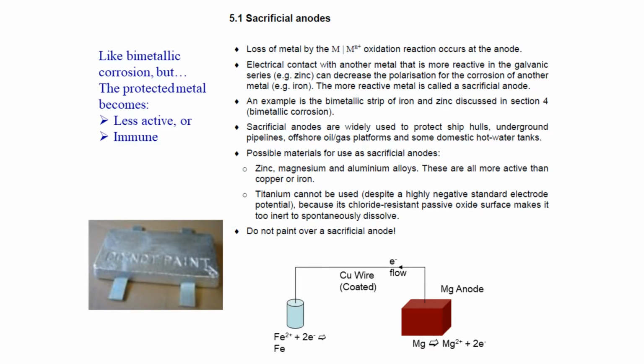Section 5.1 on sacrificial anodes talks about basically bimetallic corrosion. In chapters 3 and 4, we already looked at the algebra for bimetallic corrosion, which explained why, when two different metals are in contact in a corrosive environment, the more reactive metal really suffers badly and can corrode much faster. The sacrificial anode concept is simply the flip side of bimetallic corrosion, because when we add this reactive metal, which oxidizes faster, we also slow down the oxidation rate of the other metal.